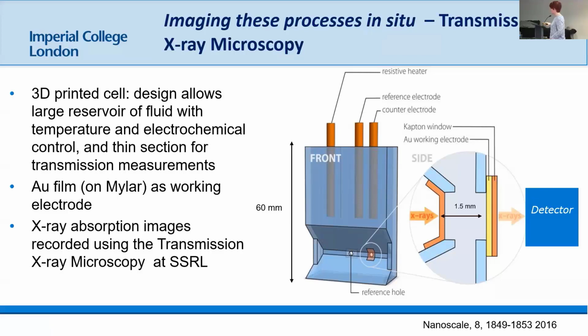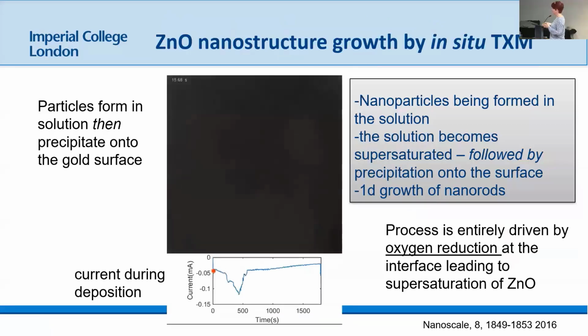And then the detector. And so what we're going to do here is just start with nothing in the system, or no bulk materials. We're going to image at the zinc edge. Hopefully this will play. Whilst we're carrying out oxygen reduction on the surface. So this is the oxygen reduction current. You'll see nothing here. It's really not very interesting because we're not picking anything up. And then slowly you start to see